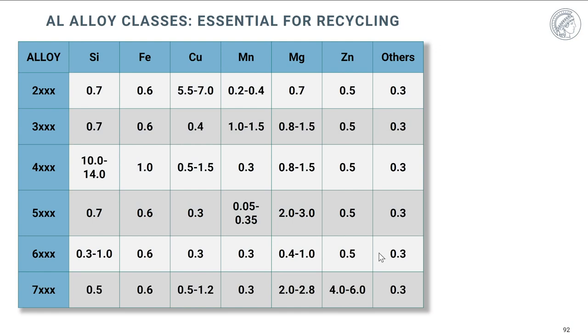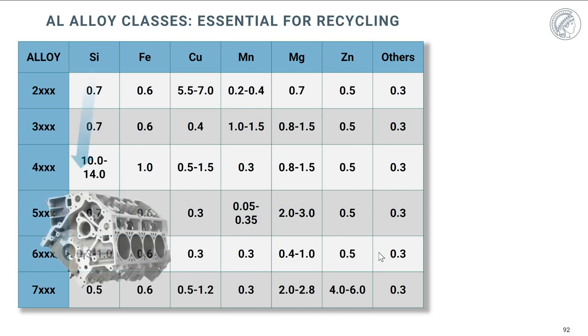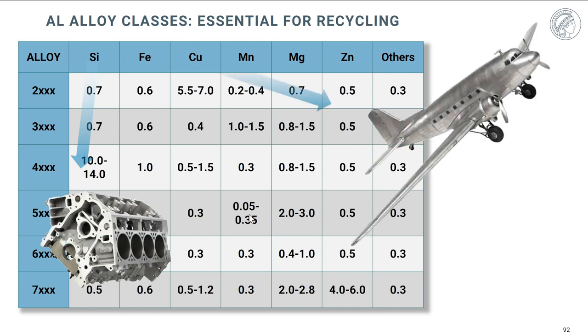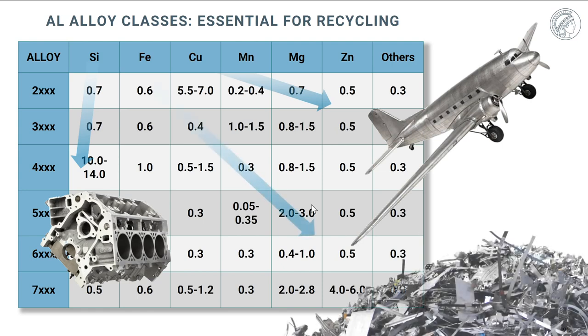However, aluminium alloys cannot be mixed very well. And you know, we have a couple of very big aluminium alloy classes, such as, for instance, the cast blocks that have a very high silicon content. We have the famous aluminium copper alloys that are used for high strength plane parts, for instance. And we have also scraps that come from mixed components of aluminium and iron, which carry a very high iron content, which is typically very undesired for aluminium.